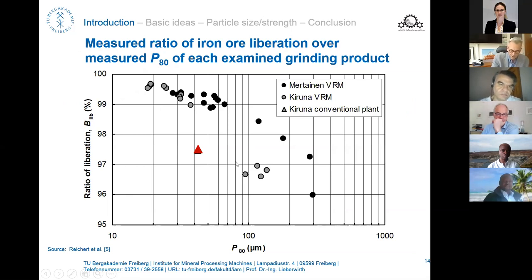Another advantage which I didn't mention, and that could be even more appealing to the industry than the energy and water savings, could be the increased recovery. Recovery still is, and will most probably be, the main driver for the mining industry. And when they see an increased recovery, all of a sudden you catch the attention of the mining people. So we did some tests with iron ore grinding a while ago already. We did the tests with materials from Kiruna or from LKAB mainly. And we also did tests with tungsten grinding in Mittersill.